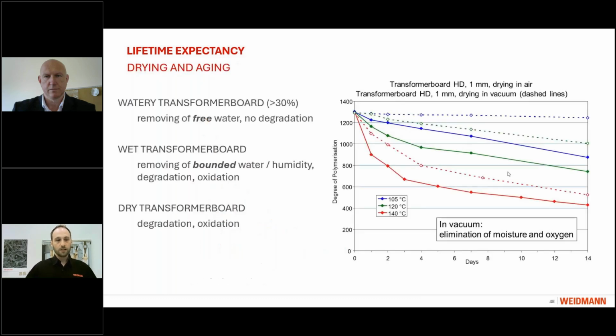First of all, when we have really moist water from the machine and the water is free, we can just press it out, no harm done to the material. As soon as we get drier and drier, removing the water gets more and more intense, and we start to see degradation and oxidation. On the right hand, you see the graphic, and you can see in blue the lines at 105 degrees Celsius, in green at 120, and in red at 140.